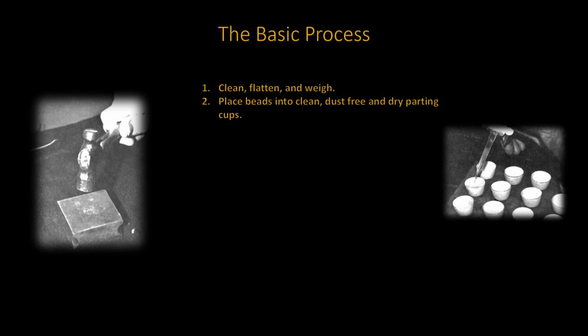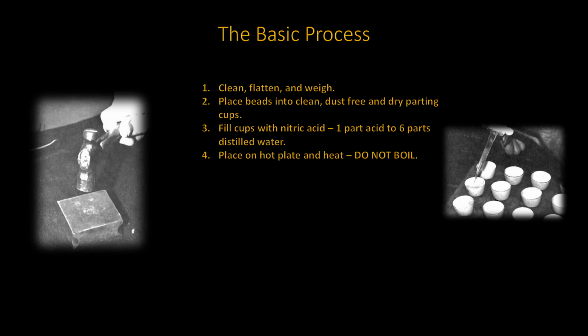Now your bead should be ready to be placed into the parting cups. The cups must be free of dust, they must be clean, and they must be dry. The cups are then filled with nitric acid. The solution is made by using 1 part of concentrated acid to 6 parts of distilled water. They are then placed on the hot plate and heated. It is important to make sure that the solution does not boil. If this happens, your gold bead will or may turn to powder.